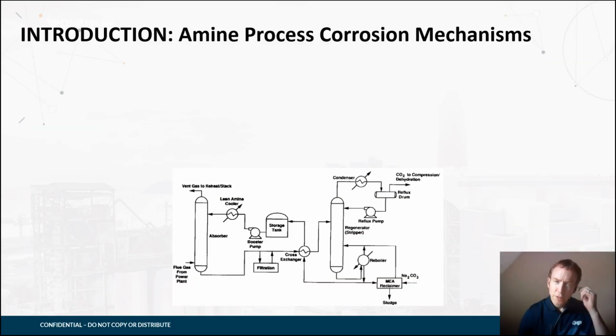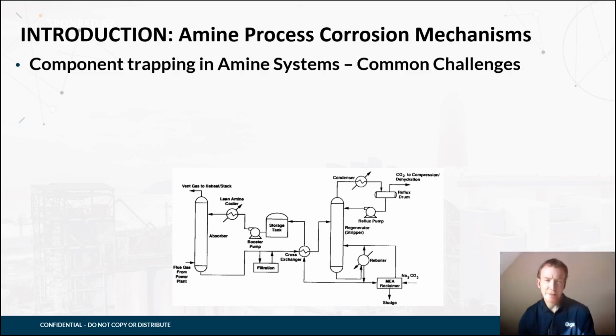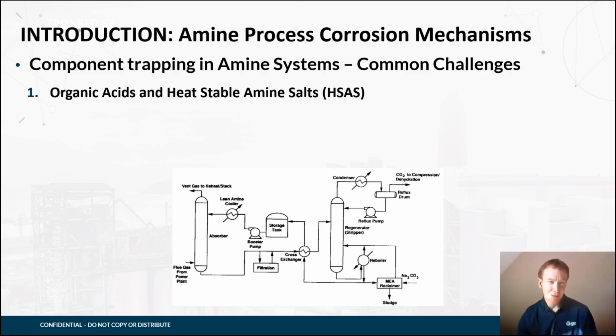As Philip discussed, in the amine systems, we have a variety of different corrosion activities that are taking place, and we need to identify a corrosion barrier system that can manage in these different environments and ensure we have protection against these separate processes and types of metal wastage attack that are taking place. So we have our organic acids, which come in typically with the feed, combined with the heat stable salts, and then are released in, for example, the hotter parts of the process, like our amine reboilers.